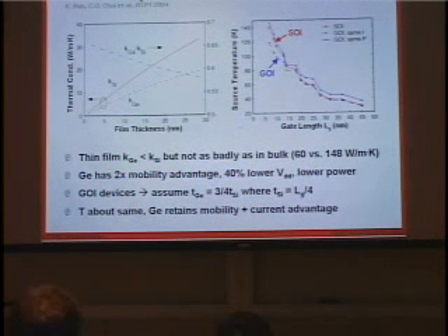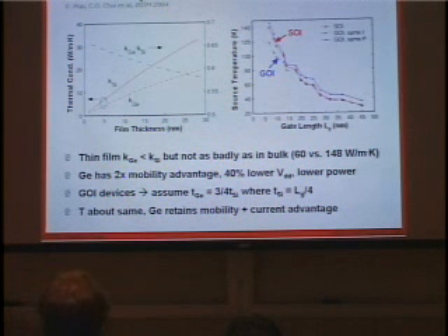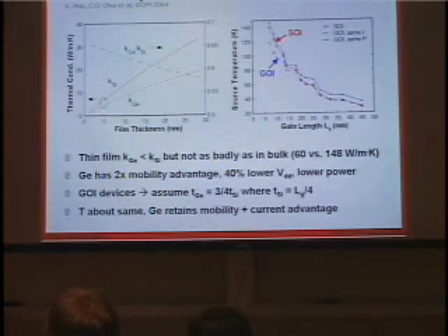Again, we're comparing SOI and germanium insulator devices. These are results from a paper which was just accepted, I found out today, at IEDM for this year. This is work that I co-authored with our in-house germanium expert, Shinan Chui. And the important thing about germanium is that the thermal conductivity of germanium is worse than silicon. Usually people have talked about germanium bulk devices as having some thermal problems because the thermal conductivity of bulk germanium is 40% that of bulk silicon.